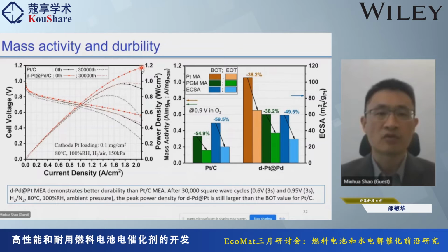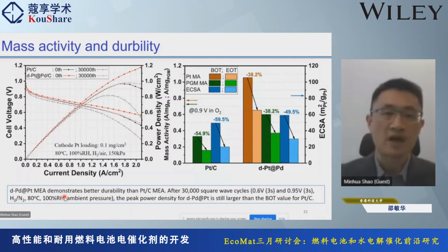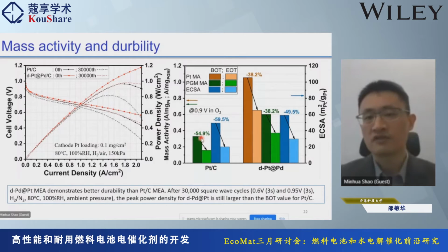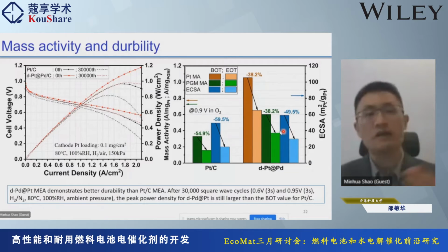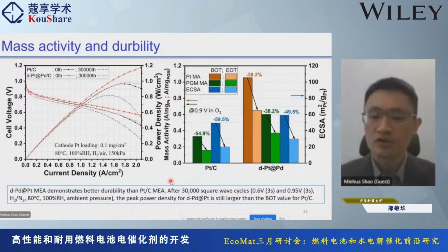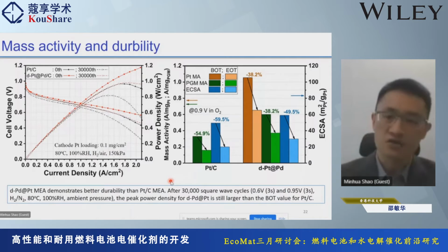Okay, the solid is before durability testing, and the dashed is after durability testing using square wave cycling. So about 30,000 square wave cycles, 80 degrees C, 100% RH. You can see that the performance decay for the core shell is actually much lower than the platinum. Okay, so if we're talking about the mass activity at 0.9 volt, for the platinum it dropped about 55%, and for the core shell it is only 38%. And the surface area drop for the platinum is about 60%, and the core shell is about 50%. Okay, so both are much lower than the platinum-based one. So we confirm that with this kind of approach, we can significantly improve the performance and the durability.